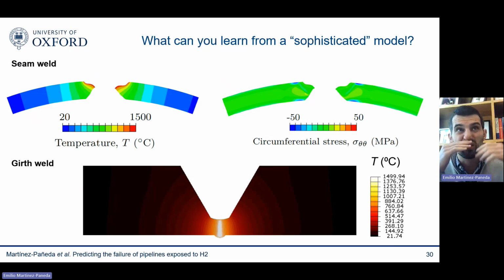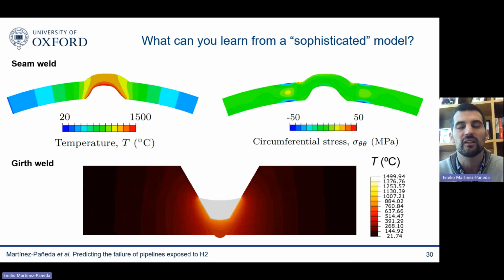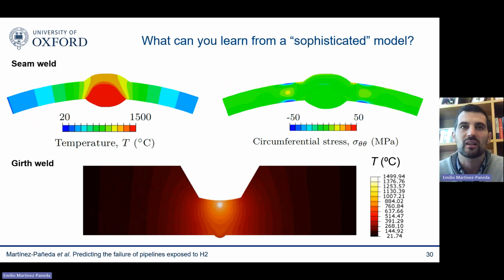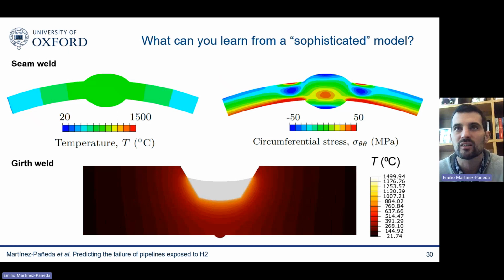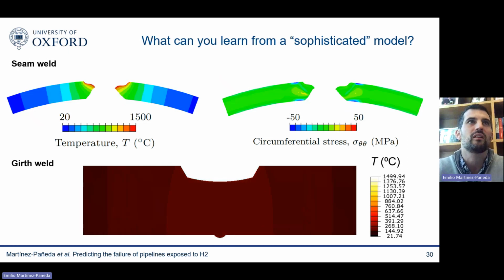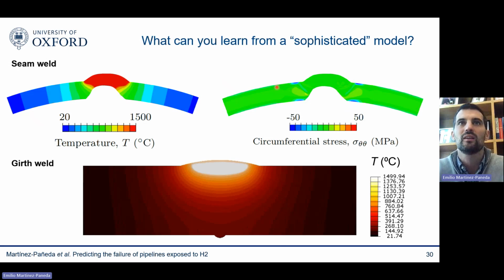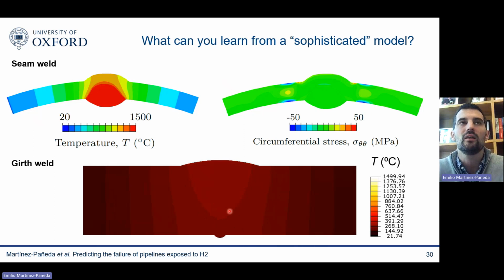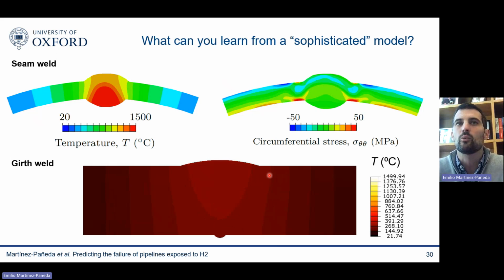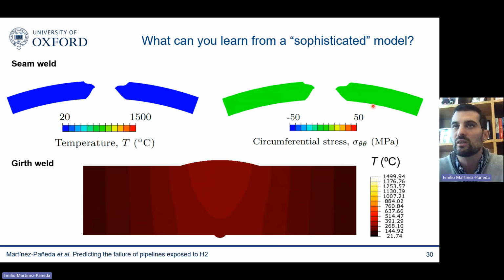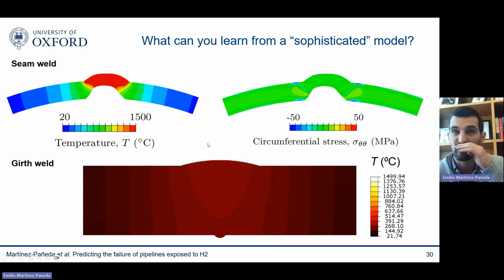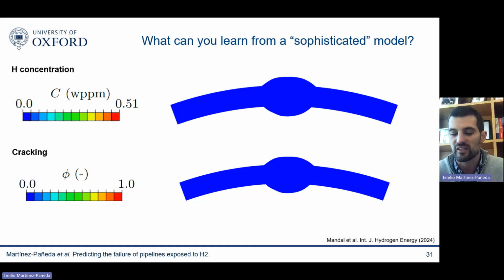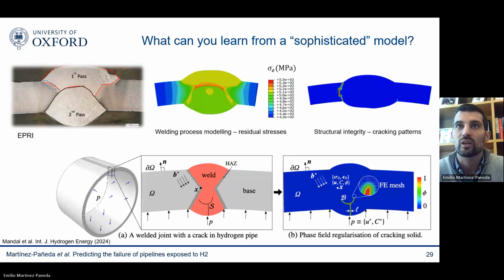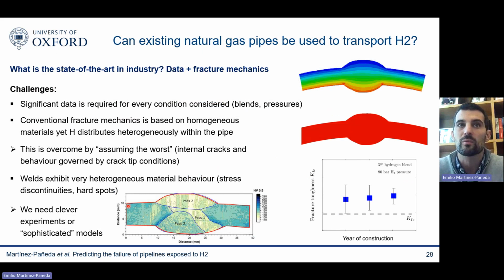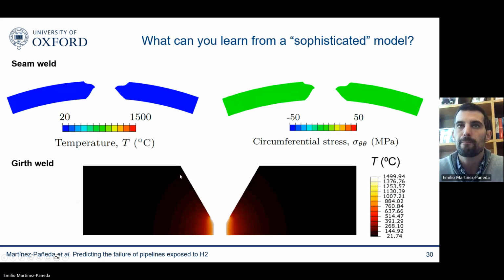So this is the welding process simulation. There's an entire community devoted to welding process modeling, and they have very sophisticated tools, so they can do these things quite precisely. You can see here the simulation for a 2-pass seam weld, and here for a multiple-pass girth weld. And you can see that basically you simulate the welding process, and then you get a distribution of residual stresses, and then you get a distribution of the phases involved in your material. And we have seen that those distributions of phases, by the way, you can correlate to hardness and deliver a very good agreement with the hardness maps that we have shown before.